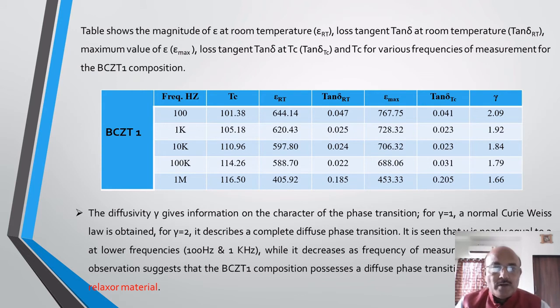Now this is the table that shows the magnitude of dielectric constant at room temperature, loss tan delta at room temperature, dielectric constant at maximum, and loss tan delta at critical temperature for various frequencies for BCZT1 composition. When we observe the table, as the frequency increases from 100 Hz to 1 MHz, the critical temperature Tc also increases from 101.38 to 116.50 degrees centigrade.